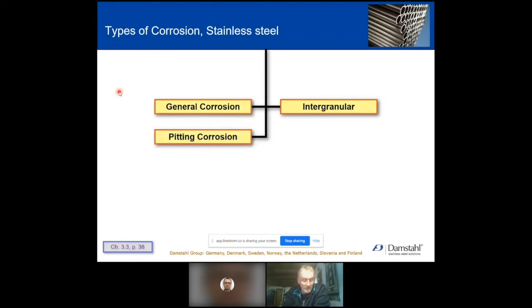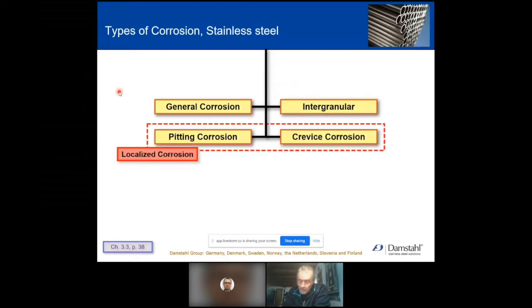Pitting corrosion, on the other hand, is very, very common, corresponding exactly to the example I gave you before. Crevice corrosion, sometimes called localized corrosion, is the same, except that it takes place in narrow geometries where you don't have any convection and all transport is controlled by diffusion. And finally, stress corrosion cracking is a combination of usually high temperature, the presence of chloride, and static stress in the steel, usually from, for instance, welding. These three are the bad guys.